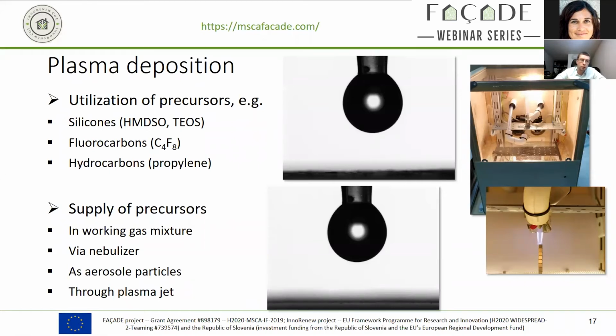The typical procedure is that this is mixed into the working gas either before feeding into the plasma or in the afterglow of the plasma. Particularly if you're using a plasma jet, then in the lower part, only after the plasma is already ignited. This can be done using nebulizers, gas washing bottles, or all these kind of things. So there's all sorts of solutions that are already available and already used industrially.